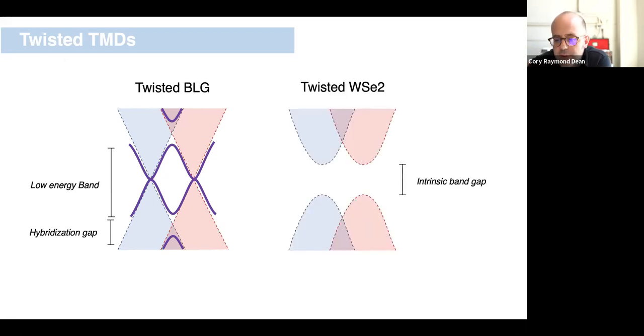For the case of twisted WSe2, or any of the TMDs, or any semiconductor really, the situation is quite different. If I had a semiconductor, in this case I'm going to look at a homobilayer, I can imagine a scenario similar to twisted bilayer graphene. I've got these two bands that are displaced in k-space. Now I'm drawing here basically the K-prime up and the K down values. I'm ignoring any higher energy or lower energy bands. There again is the opportunity for these bands to hybridize.